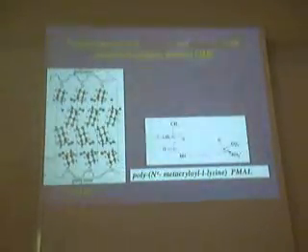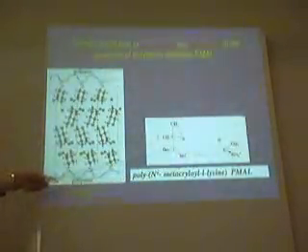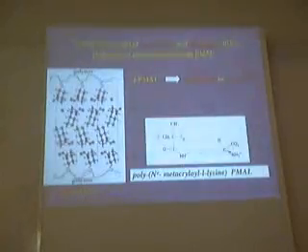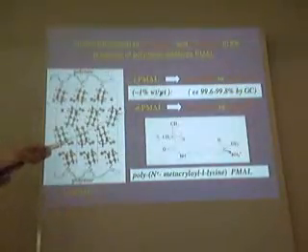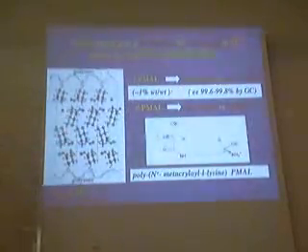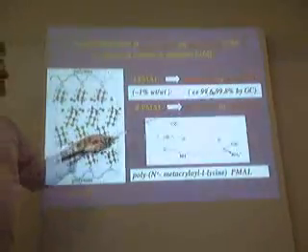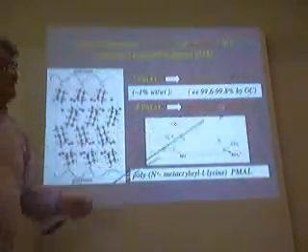What happened here is that if you now had a polymer, methacrylic acid, to which you have attached lysine, let's say it is L-lysine, and you add this to the solution, then with 1% or even less, you can remove completely the lamellar twin. You can get 99.6, 99.8% by GC.